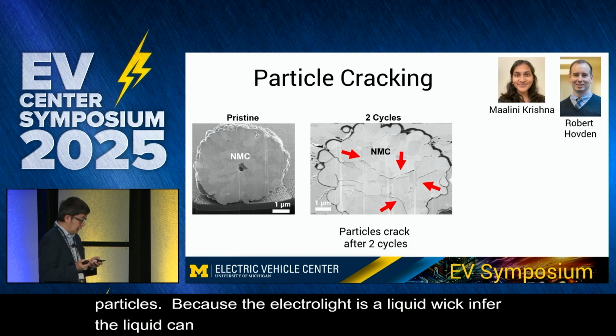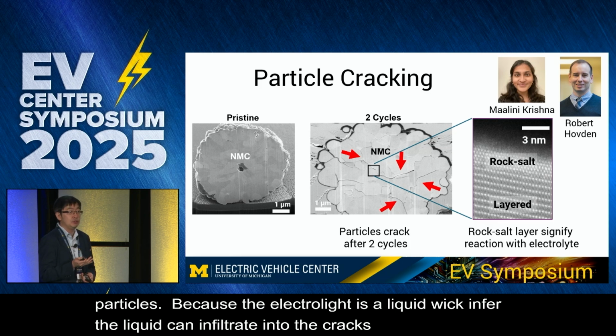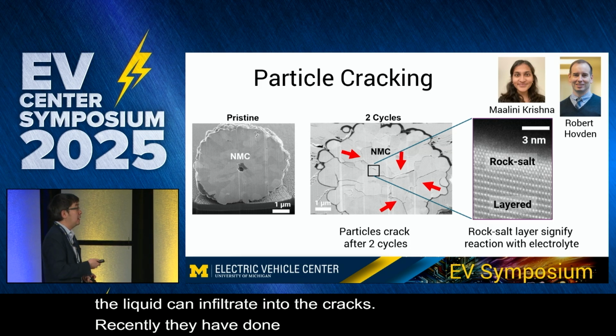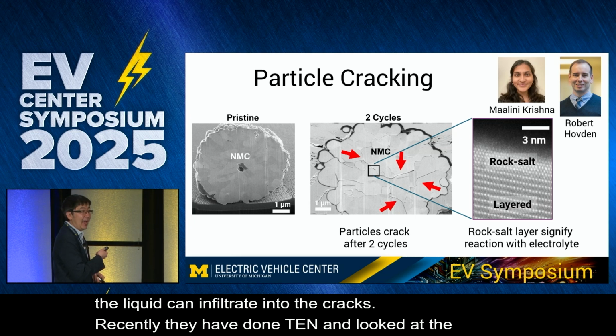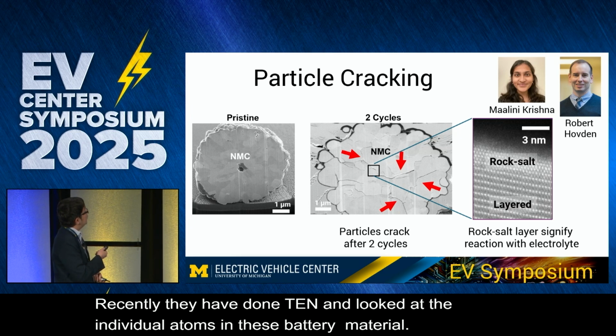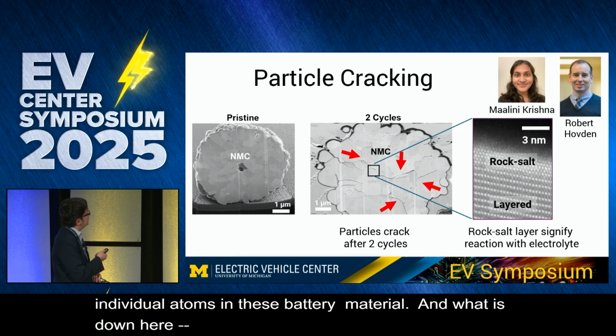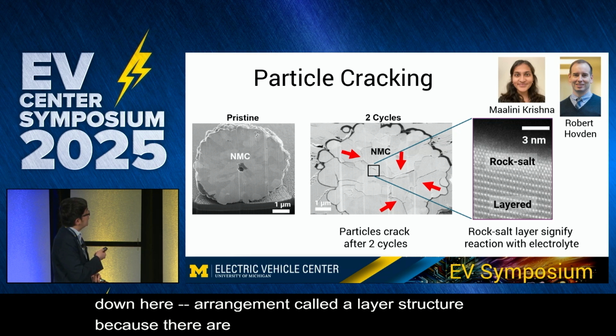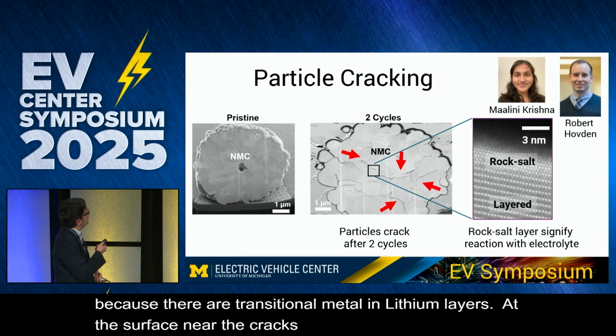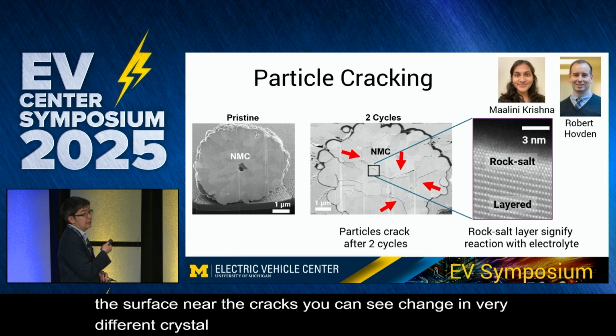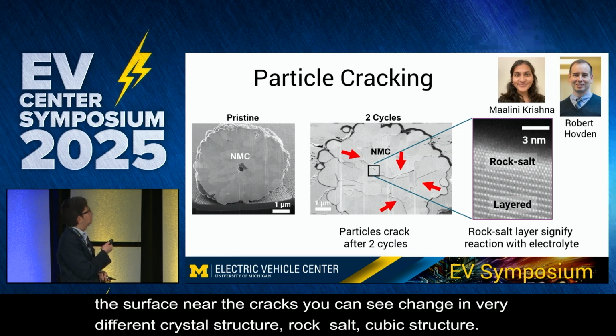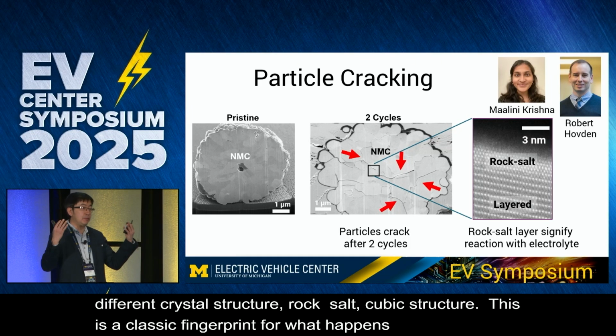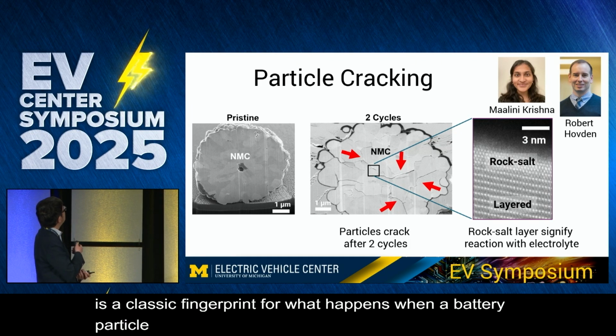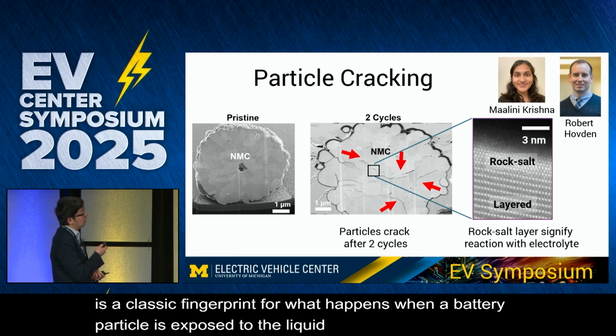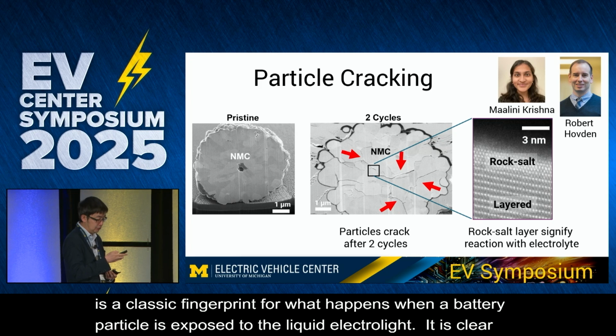these cracks. So very recently, they've done some TEM, transmission electron microscopy, here at the MC², where we looked at the individual atoms in these battery materials. And what it sees is down here, we see the arrangement. They call this a layered structure because there are these transition metal and lithium layers. But at the surface, near the cracks, they can see a change into a very different crystal structure. We call this a rock salt. It's a cubic structure. And this is a classic fingerprint for what happens when a battery particle is exposed to the liquid electrolyte. So this tells us that even though these cracks are very small, it's clear that the particles are being exposed to the liquid electrolyte up top.